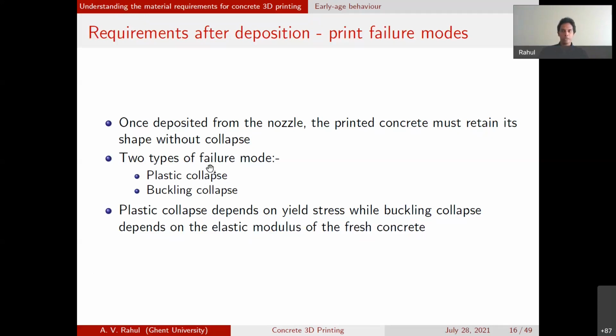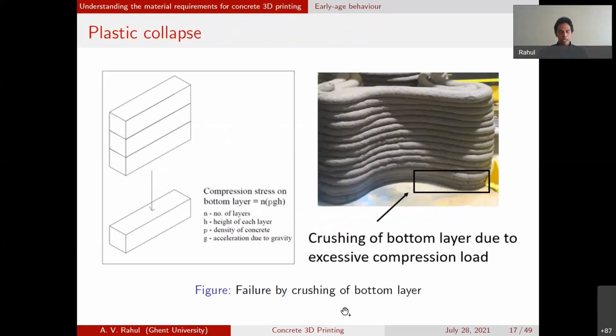Now, for the fresh 3D printed structure, you can have two types of collapse mechanisms. One is a plastic collapse, and the other is a buckling type of collapse. So I will look at both of these in detail. A plastic collapse happens when the weight on the bottom layer becomes too much and flow is initiated in the bottom layer. As more and more layers are built on top of it, there's more shear stress exerted on the bottom layer. Once it exceeds the yield stress, the material would start to flow, as you can see in this image here.